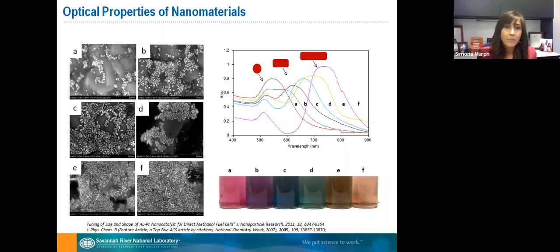You can see here on the left, we have the SEM images. As we increase the length of these rods, going from sphere to rod, and we go from 30, 40, 80, we can tune the length of the rod. You can see that we can tune their optical properties. I just mentioned the surface plasmon bands. When you have a sphere, the electrons go in each direction, so you have one peak. What you can see here for the spherical nanoparticle is this plasmon band for the gold nanoparticles. Once you get to the rods, the electrons oscillate along the short axis and along the long axis. That's why this band is split in two. So for the rod, depending on their length, you can have a different plasmon band.